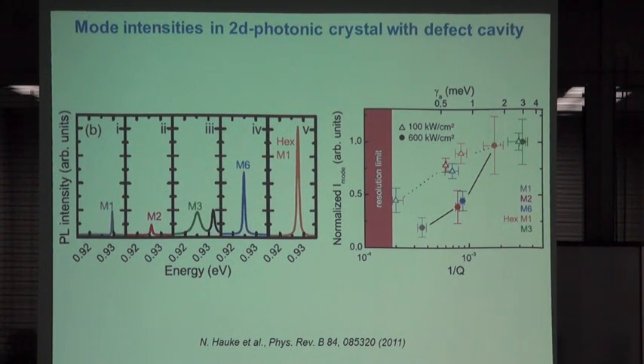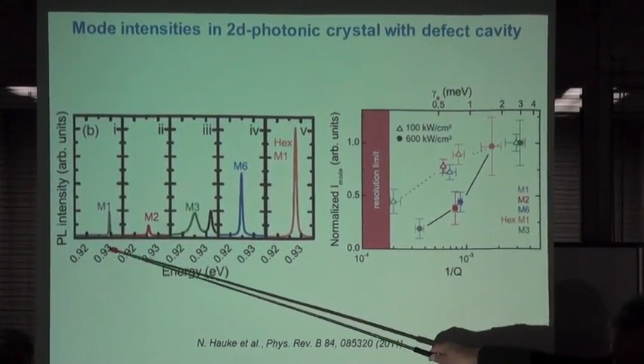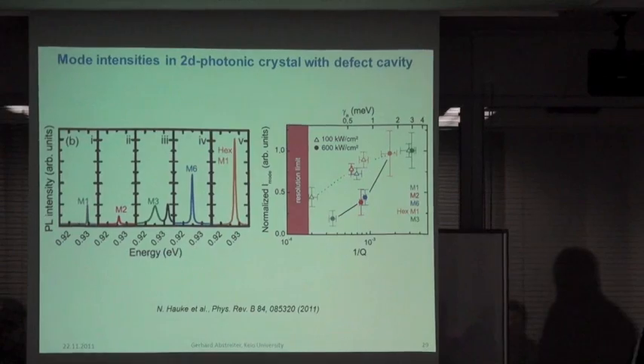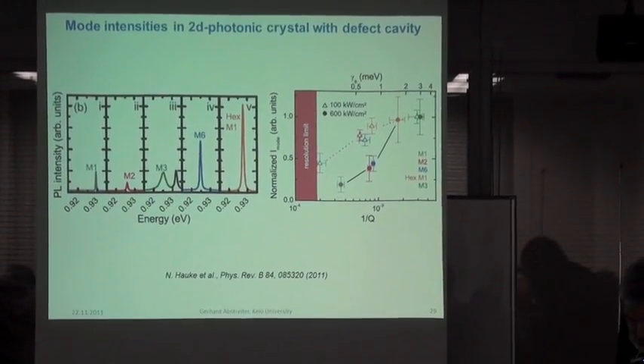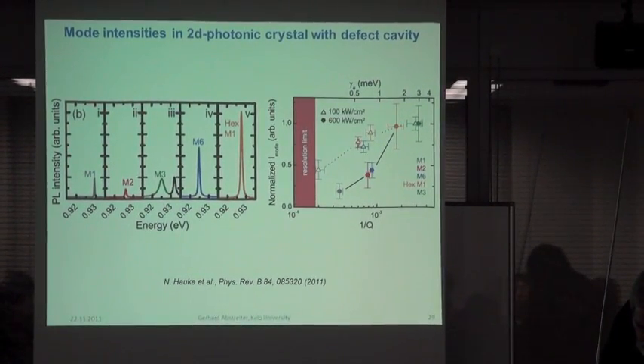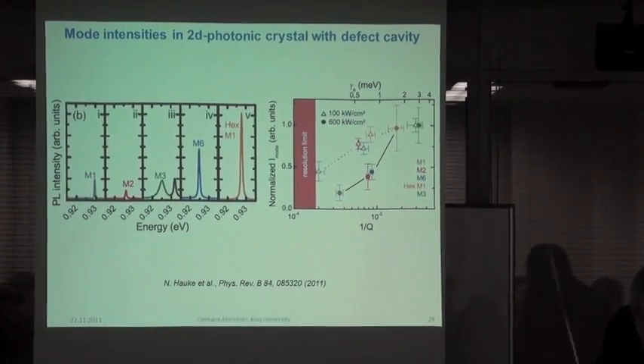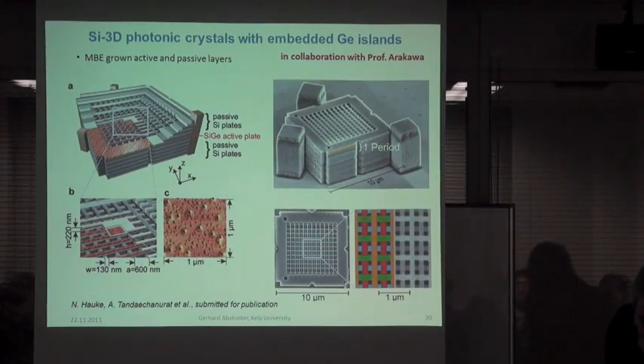How many dots are you coupling to the cavity? We believe that we couple roughly 100 dots to the cavity in this regime here. It's not a single dot. And then you average, and it depends on the detuning also, because you couple also if you're not exactly tuned because of the broader width of the oscillator. And that's why the total intensity, even though it's a very narrow line, goes down when Q is improving. This is the reason. So when you want to make in silicon an efficient light source, Q should not be too high when you use this as an emitter.